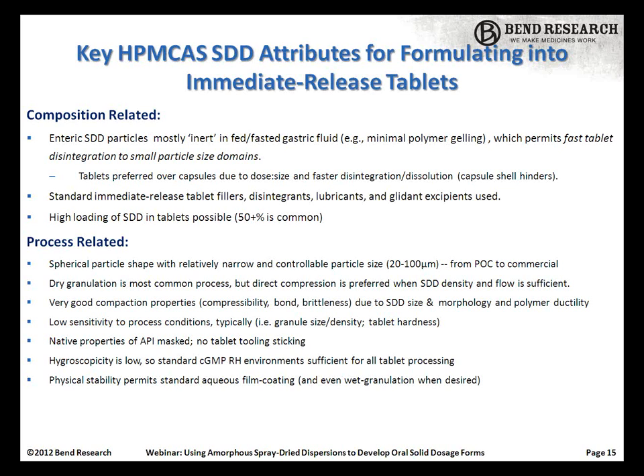The particle size, from the very early batches up through commercial, encompasses a range of maybe 20 to 100 microns, most commonly. Dry granulation is possible, but if the loading of the dose and the properties are such that we can do direct compression, that is our preferred process. One important thing is the properties of the particles. Compaction properties are actually very good. I would say they're similar to excipients, maybe somewhere between Avicel and lactose on compressibility, ductility, and bond. So compressibility rarely is a problem.